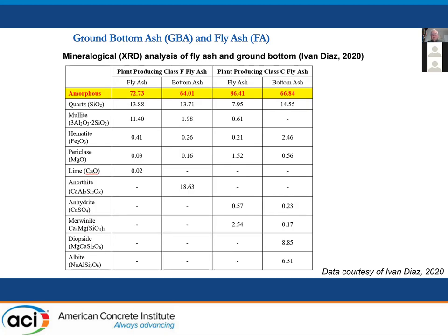One issue that's been raised, and again, this is some of Ivan's data, is whether the glass content is the same, since we want the amorphous aluminosilicates to provide the reactivity as a pozzolan. And it shows in this example that the bottom ash has a lower glass content, or amorphous content, because it probably cooled more slowly than the fly ash.